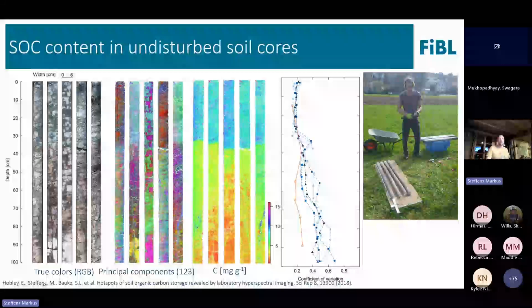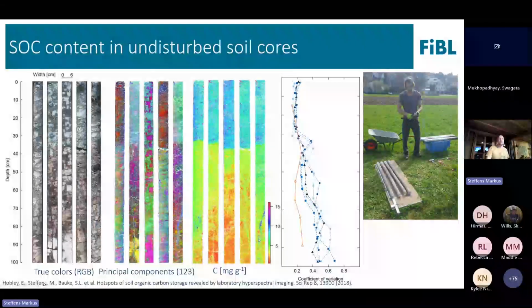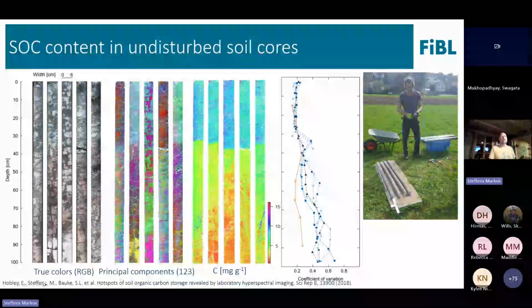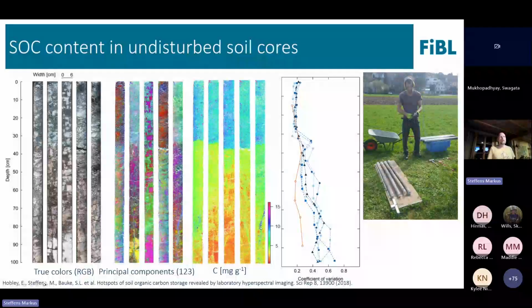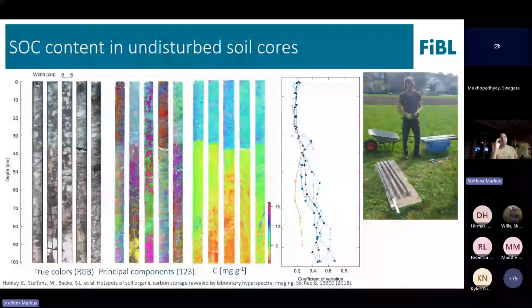Other features that appear is this structure or this feature here, which is either an old root channel or from an earthworm burrow. And the last one here, there you see the variability of the carbon with the depth. And of course, as you can imagine, the carbon is quite homogeneously distributed in the AP horizon, but it's getting much more heterogeneous and variable in the lower parts.